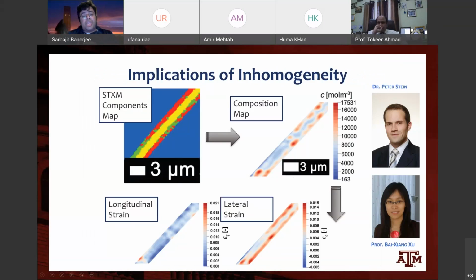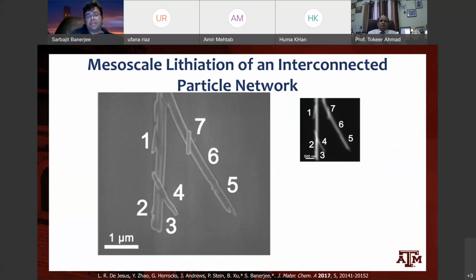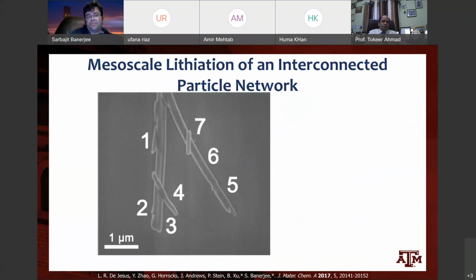And anytime there's a strain and you have a brittle material and you cycle it, what happens? Fracture, right? So the particle will end up breaking, and this is why, as your cell phone becomes 1 year old, you get less and less capacity out of it. Even though it's telling you that your phone is charged 100%, you're not getting enough capacity, because more and more of your cathode material is perhaps no longer accessible to do energy storage because it's cracked off, right? So this is some work with Dr. Peter Stein and Professor Bai-Xiang Xu's group at TU Darmstadt looking at these stress inhomogeneities, and they're really critical for many things, right?